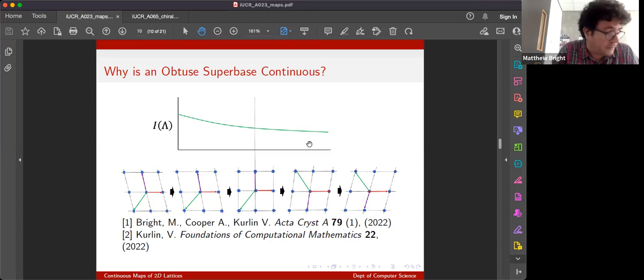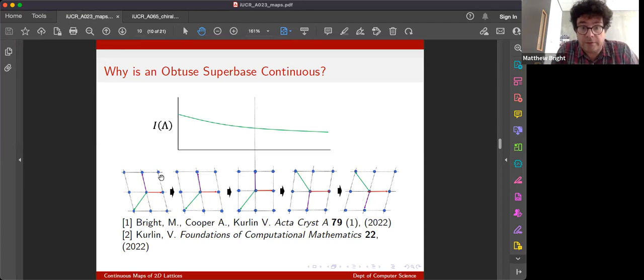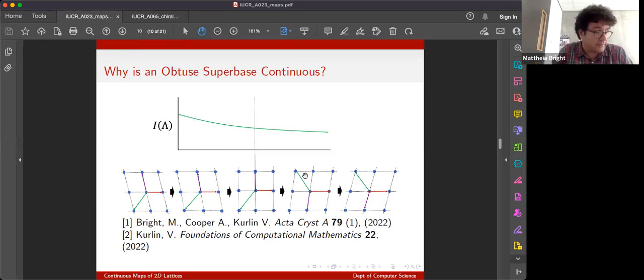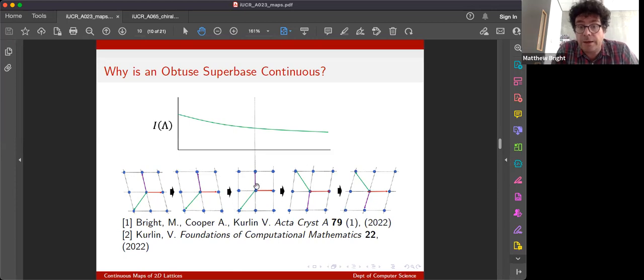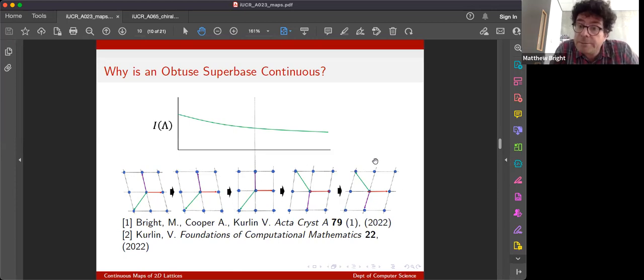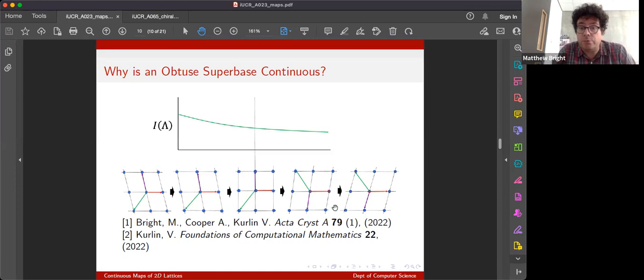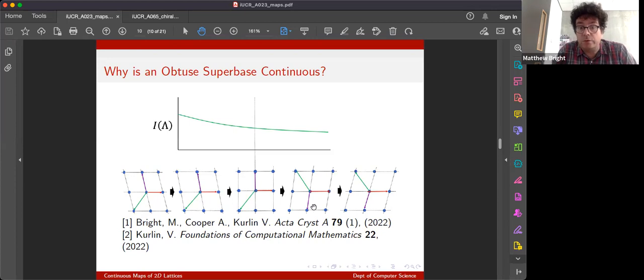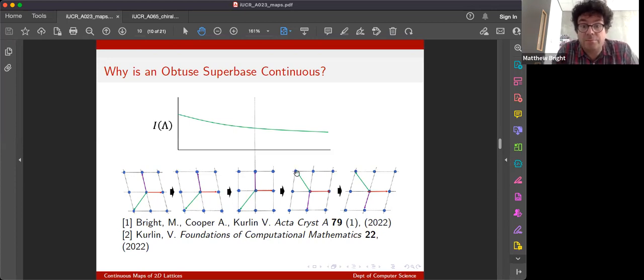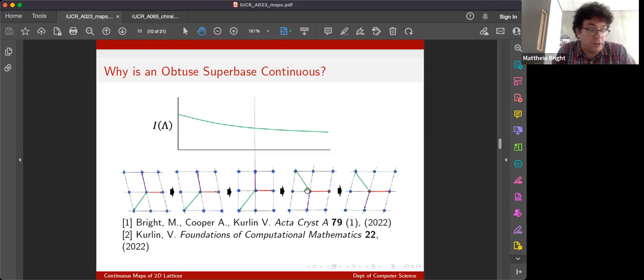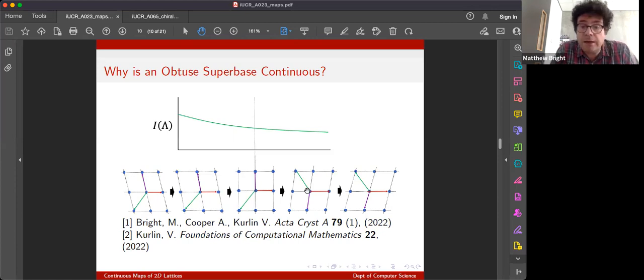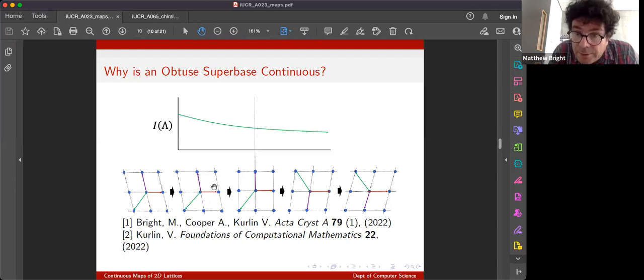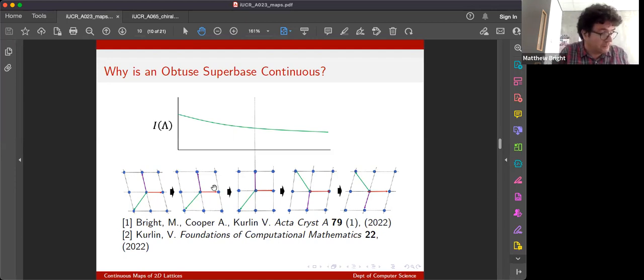But essentially what we're illustrating here is that as I, again, as I slowly deform this two-dimensional lattice, if I pick any pair of vectors, they're going to appear to change discontinuously as they did before. But if we keep all, if we keep track of all three vectors, what we see is in fact happening in any given pair is that one of them is being replaced by the third continuously changing vector that we keep track of. So really what's changing is the order in which we're looking at these vectors. Their parameters are changing continuously.